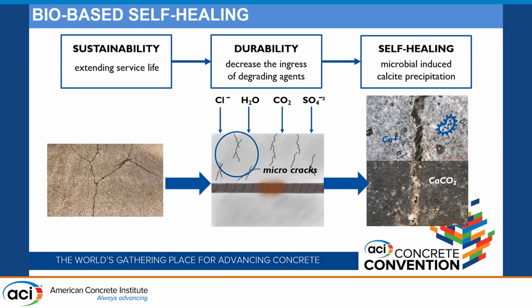Therefore, when we take into account the high carbon dioxide emission of the transportation and production phases of concrete or cement, one way to reduce the environmental impact of concrete is to increase the service life of existing construction. For extending the service life of existing construction, it is required to provide and protect the durability of the concrete. Chemical and physical durability of the concrete and the reinforcement in the concrete directly affect the maintenance of the existing construction. Microcracks contribute highly to durability problems such as carbonation, corrosion, abrasion, and so on, due to the increased permeability of the concrete, which is unable to prevent the infiltration of detrimental components.